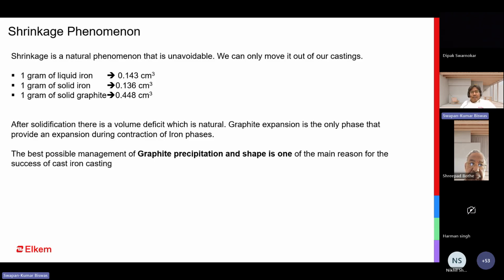So whatever carbon you are using in the furnace, that recarburizer should convert into the free carbon, which is called graphite. So when your graphite precipitation and distribution is very good, definitely it will help to control most of the metallurgical related defects. When expansion is going on with this graphite, you need more graphite precipitation.